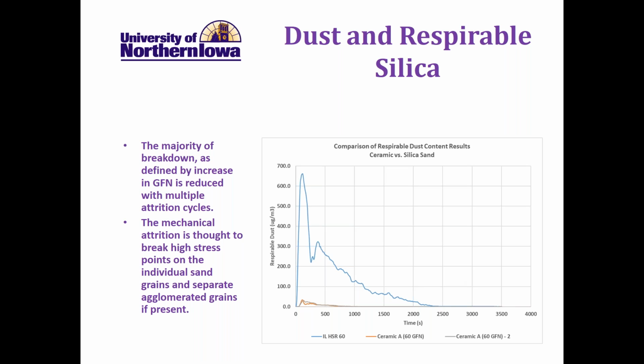So what we're seeing is, this is a new Illinois high silica round 60 GFN sand. The sand hasn't been used in an operation. It is strictly a representative sample off a load of sand. We can see peak respirable silica of over 650 micrograms per meter cubed, while the ceramic A, which was tested twice, was under 25 micrograms per meter cubed. A dramatic difference.